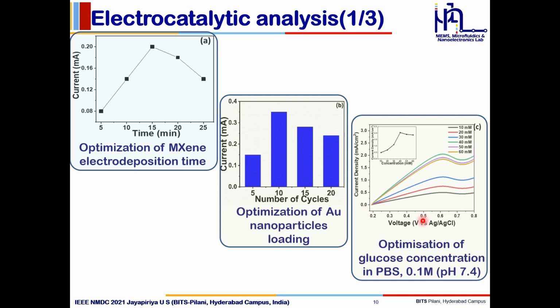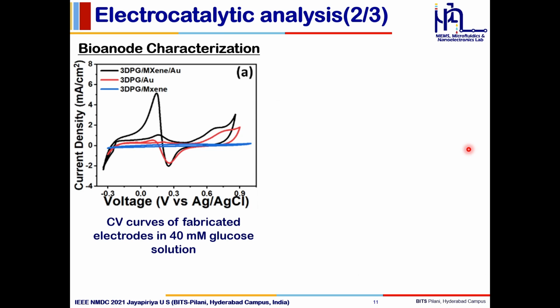Also, the glucose concentration in which the bioanode has to perform was optimized using linear sweep voltammetry in a concentration range of 10 to 60 millimolar. It was found that 40 millimolar gave good performance and was used in the experiments. The bioanode characterization was done using cyclic voltammetry in the potential range of -0.3 to 0.9 volts with a reference electrode of Ag/AgCl saturated in KCl. It is clearly understood that in the presence of MXene and Au on the 3D printed electrode, well-defined redox peaks were observed corresponding to glucose oxidation.